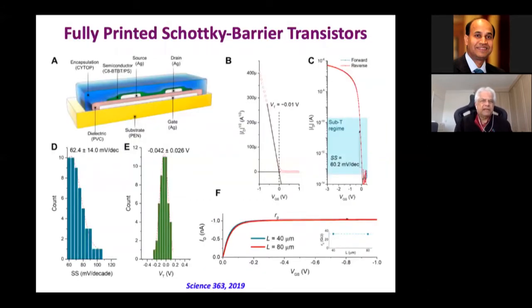So here's the fully printed Schottky barrier transistor. What you saw earlier was the ohmic, but the whole idea behind the ohmic was to figure out what best process steps one could use to reduce the interface state density. Now we've gone to the Schottky, where we have a very wide band gap semiconductor. This is a C8BTBT polystyrene blend. That's a wide band gap material, and like I mentioned, a wide band gap material gives you a low off current.